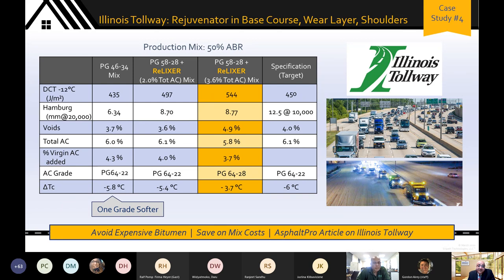So you can see here are the mix properties made with one grade softer. Here are the mix properties made with a bio-based rejuvenator. It was put down well over 20 lane miles over 6 or 7 days worth of production, 20 lane miles before we walked into their spec books as a qualified material. They were not only pleased with the bio-based rejuvenators, they asked us to increase the loading of the rejuvenator and put down some roadways because they wanted to tighten their specs in order to be able to meet better requirements.